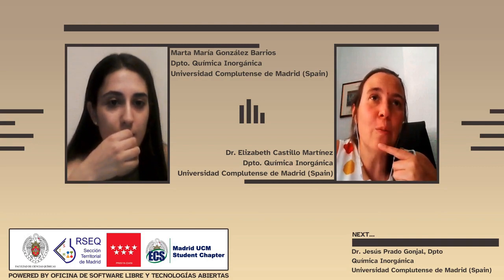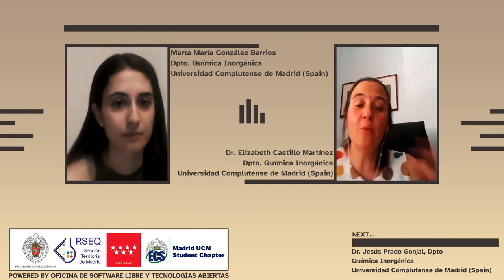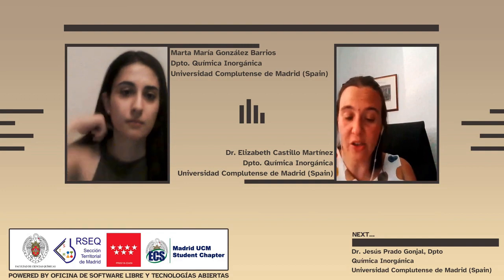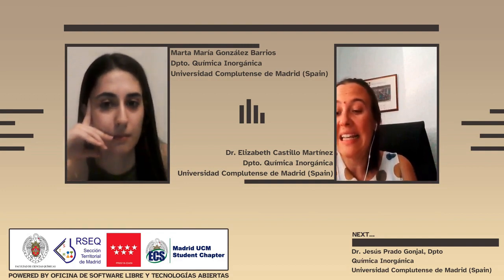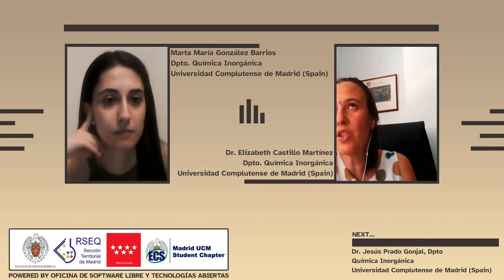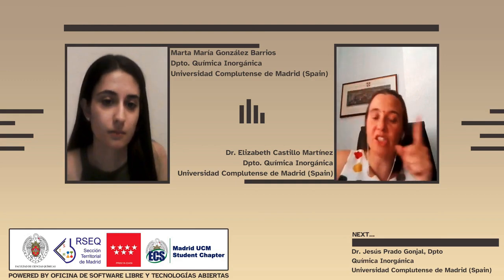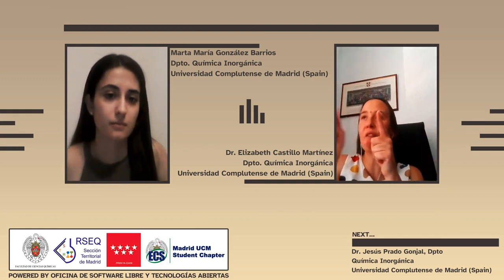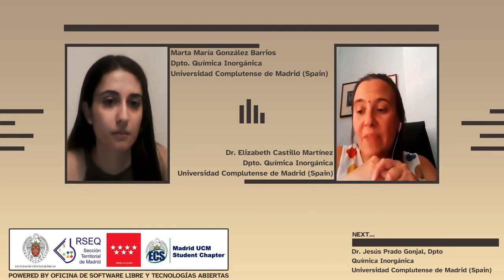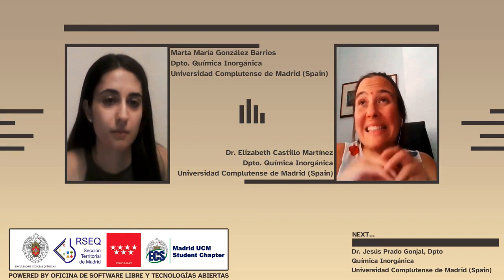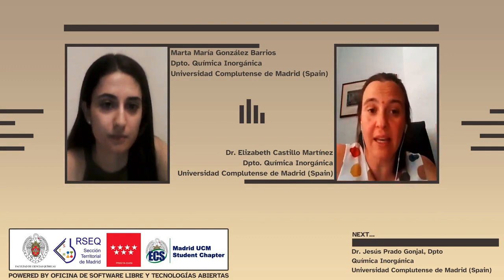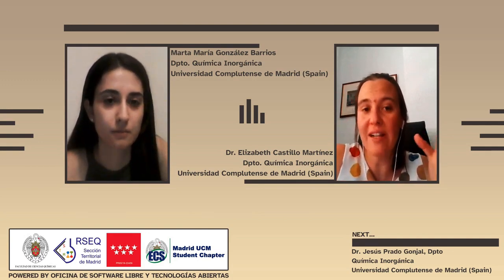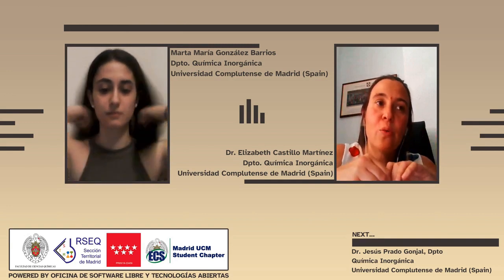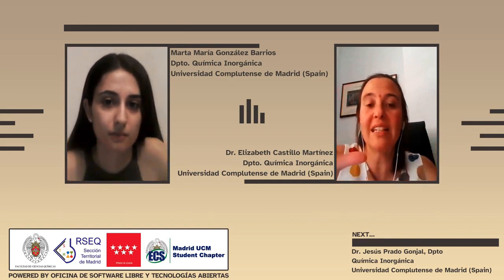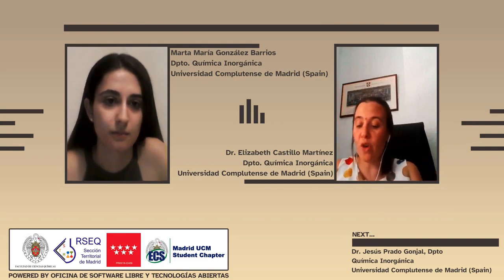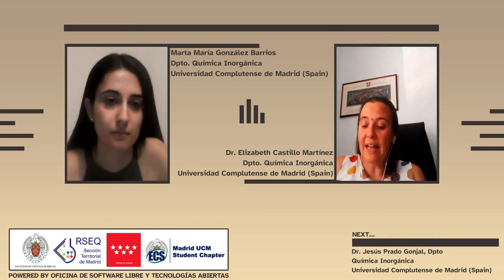You can use the lithium metal as a counter electrode and as a source of lithium, or sodium metal as a counter electrode and as a source of sodium, but it is better, if you can, to use another electrode which has, for example, a flat voltage plateau, and get this material in the middle of this plateau to act as a reference electrode material. However, this electrode material has to be a very good electronic conductor to have a good reference electrode. So it's not that easy. So what you can typically do is do the measurements in a 2-electrode configuration using the sodium or potassium metal as your counter and reference, and then do other measurements.